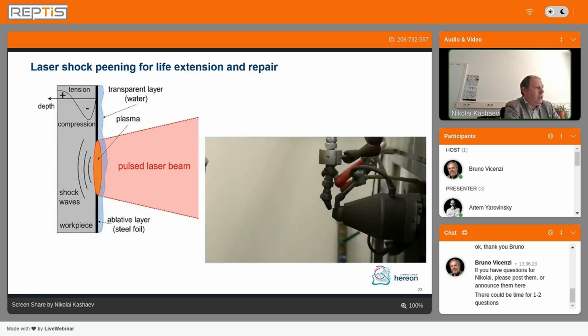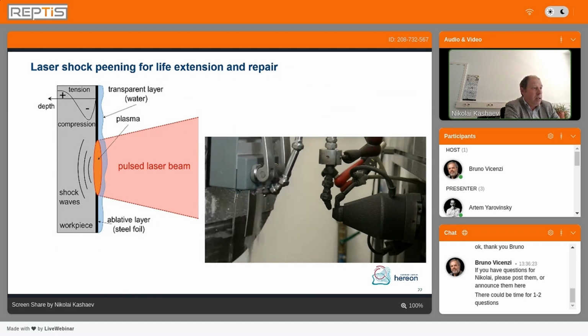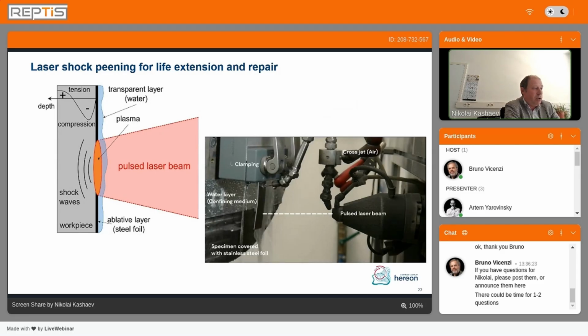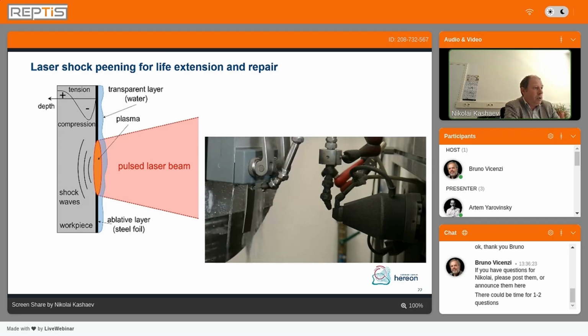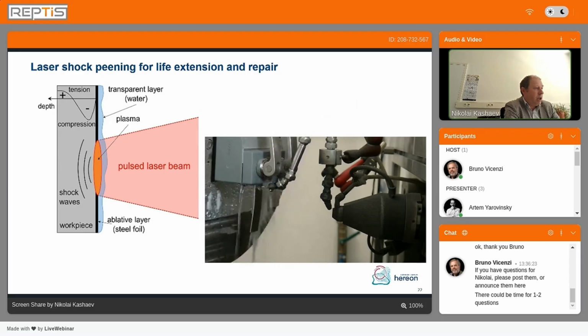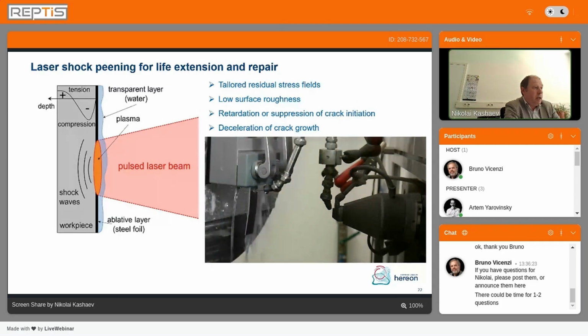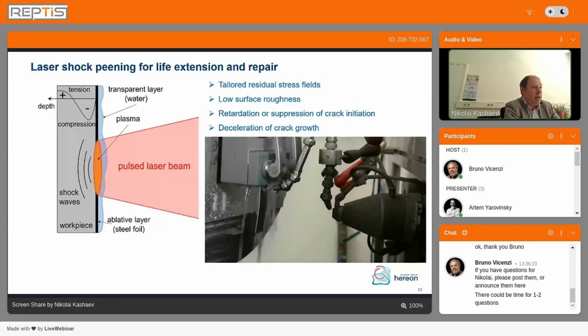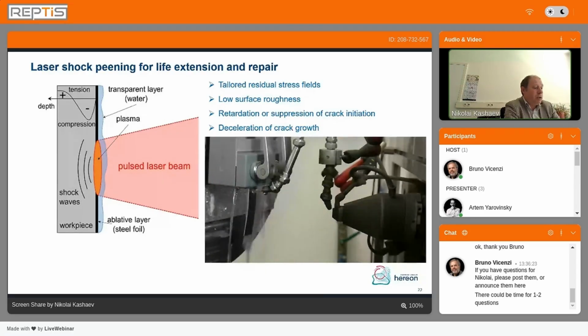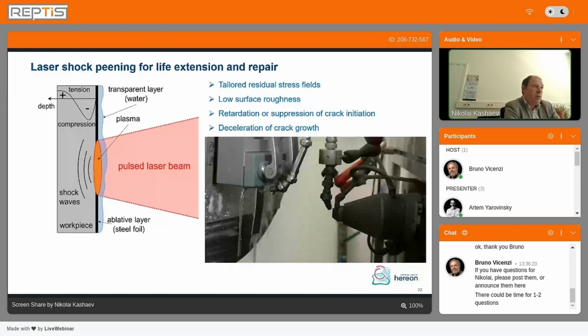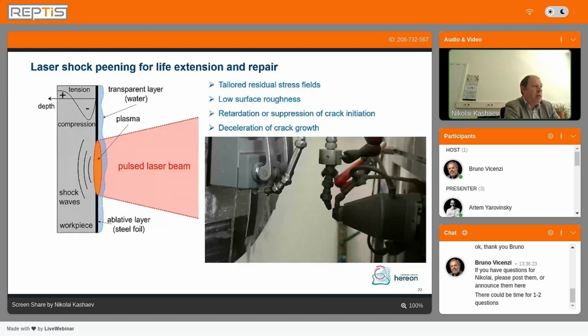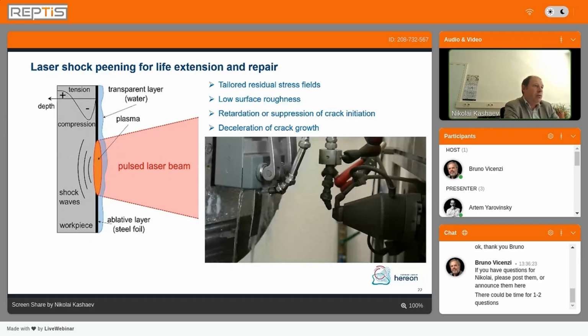Another interesting process we are working on in our laboratory is the laser shock peening process. The process is shown schematically here with a video sequence. We use a high energy laser to introduce shock waves which propagate through the material and result in deep plastic strains. As a result, we can introduce deep compressive residual stresses at lower surface roughness, and the process can be effectively used for retardation or suppression of fatigue crack initiation or deceleration of fatigue crack growth.